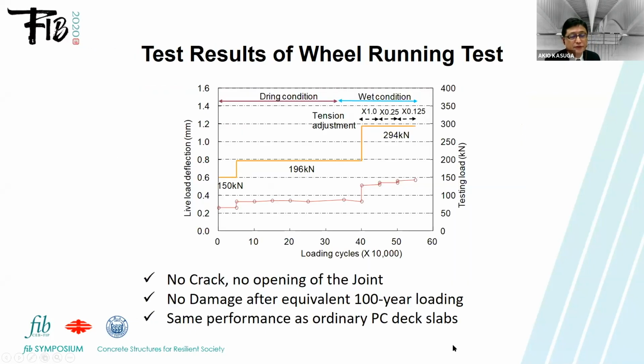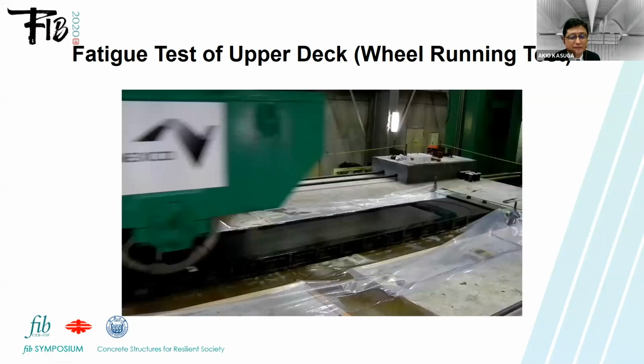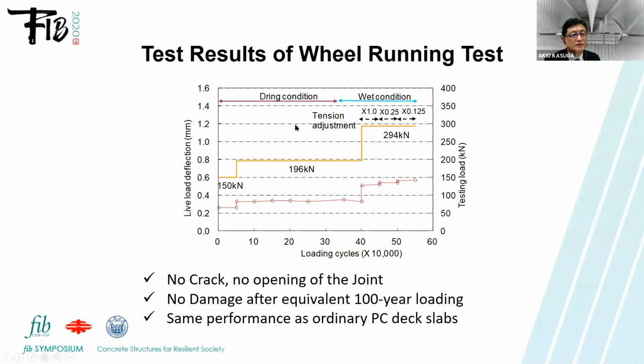This is a special test, and also this is equipment owned by the highway company. And this is the result of the wheel running test. The deformation is constant after the wet conditions. So finally, no crack, no opening of the joint, and no damage after this, which is equivalent to 100-year loading. So this is this new technology. The performance is the same as the conventional ordinary reinforced concrete deck slab.